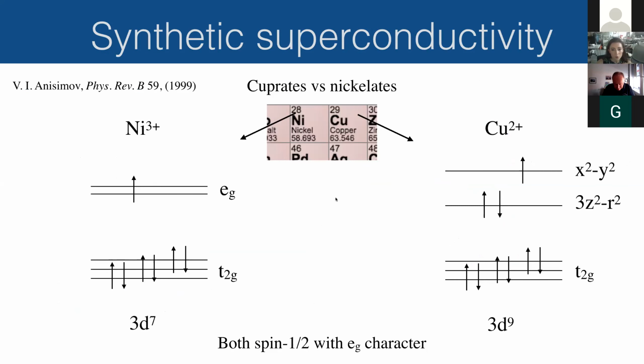So why did we want to look at nickelates in the first place? Cuprates are very famous high temperature superconductors. Still not room temperature superconductors, so we need to make some more superconducting materials to try to find that. And a lot of people thought that maybe nickel, because it's right here next to copper, could be the way to go. In particular, the high temperature superconducting cuprates are copper 2+ ions in the parent compound. And the rare earth perovskite nickelates are nickel 3+ nominally. So they actually look very similar in that they are both spin half and they both have eg character. So this was not a bad place to start from.